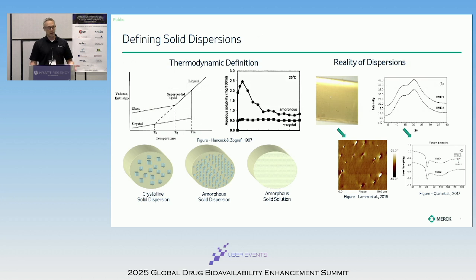So with that intro out of the way, talking a little bit about solid dispersions. I think everybody at this stage in the pharmaceutical industry life cycle is pretty familiar with what a solid dispersion is. Essentially, you're taking and transforming a crystalline active ingredient into an amorphous material to leverage the benefit of the increased free energy to enhance the solubility of that molecule. And oftentimes what we see is that amorphous APIs on their own are not physically stable, and so they're going to revert back to their crystalline form. So we work to stabilize those through the incorporation of excipients into that material to reduce the tendency for crystallization.